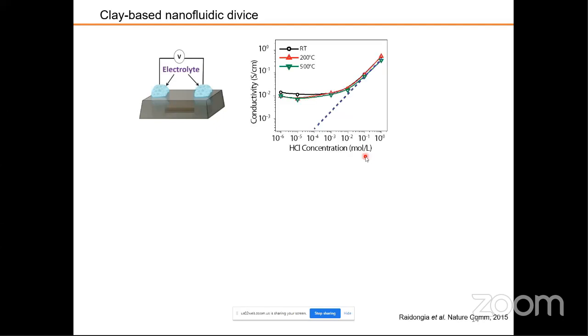For that, we can put a reservoir here, which is connected to our nanofluidic channels, with different ions. For example, here we have used HCl, where protons, that is H plus ions, can go through the channels. If we measure the conductivity between the reservoirs, which are not connected directly, only through the nanofluidic channel, we can measure the conductivity of the channels. And here we changed the concentration of these electrolytes and measured the conductivity. Here we put the concentration of different electrolytes, and here the conductivity.